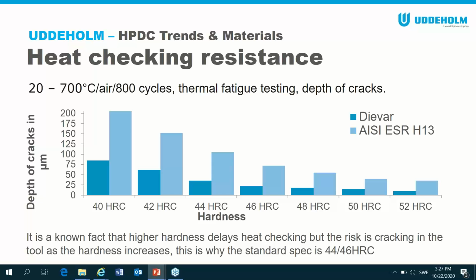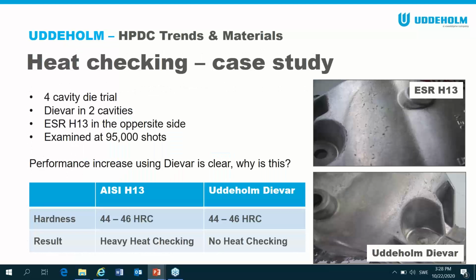But you notice that starts to get less and less as you go up to 52 Rockwell. But the problem there is, as you go up in hardness, of course, you sacrifice toughness. And that's why NADCA tends to stick to 44, 46, because for most dies, that's a safe area to be. So the question is, what happens to Dievar once you go out of the NADCA safe zone, 46 Rockwell, and go higher, to try and get that better heat check resistance? If we just look at a case study, I'll answer that question in a second.